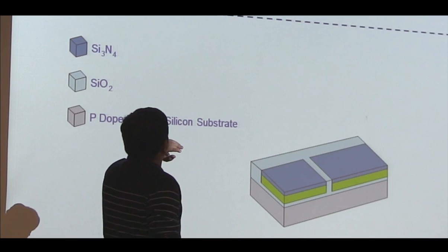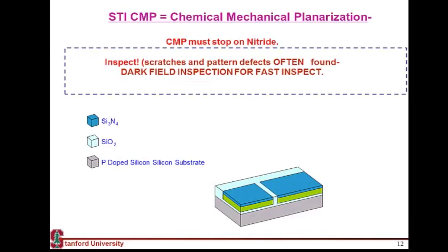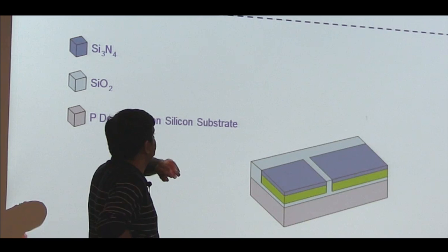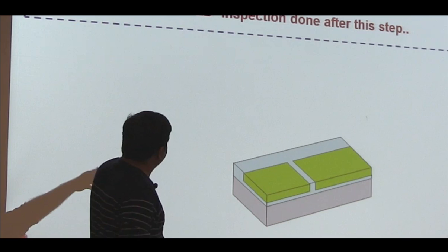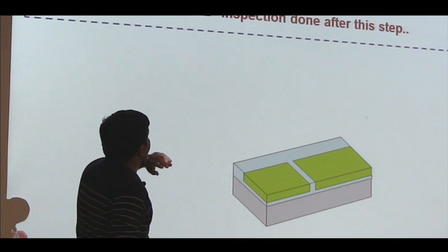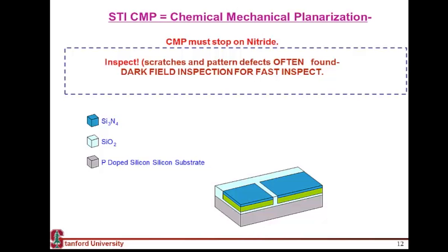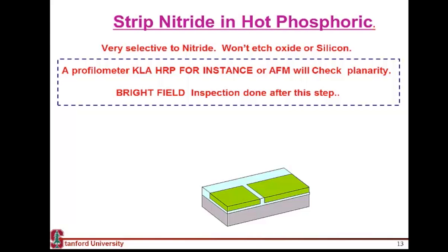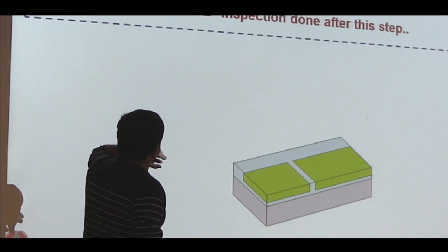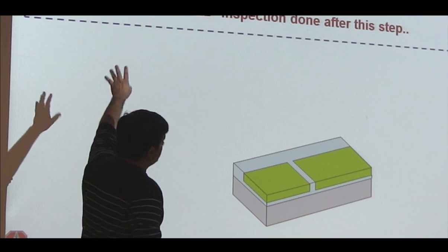Or sometime you use films which are flowable, so you fill them and they flow in. And they flow in and fill your feature. A good thing is that when you make smaller features, your capillary force actually goes higher. So capillary force is inversely proportional to the distance between, or it's inversely proportional to your, I think it's the third power of your feature size. So if you have a smaller feature, your capillary forces in fact increases. So it tends to pull things inside. So that's one of the forces which is leveraged to fill smaller features. So the next step you do is essentially you fill this feature, you polish it. And the process which is used is the CMP, or chemical mechanical planarization. This is one of the processes which causes a lot of your defects, or caused from this process. Because even if you have one defect, and the way CMP works, it's like a grinder. So even if you have one particle, it will grind all over your wafer. And so again, what is needed is an inspection step after you do this process. And then you come and remove your hard mask. And in this case, the hard mask was nitride. So you can use a chemistry like a phosphoric chemistry, which can remove your nitride. And it's very selective to nitride. So again, after this, you need to make sure that it's flat. So there's another inspection step. And then in this case, it's a bright field inspection step since we are checking for uniformity.